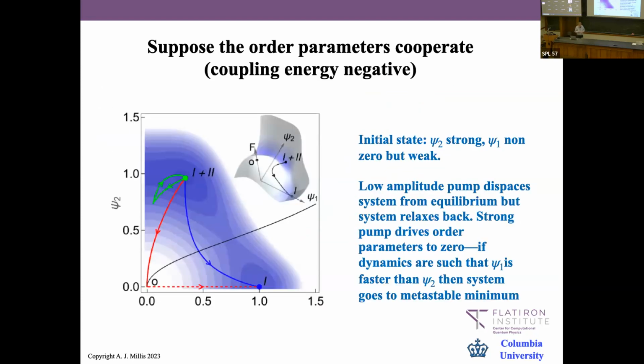You can do this in a slight variant: say the order parameters cooperate instead of compete. Then if you have a system which is mostly charge density wave but slightly superconducting, the favored minimum is slightly off zero, but you get the same story—for weak pulses, you just go a little bit away from your minimum and go back.